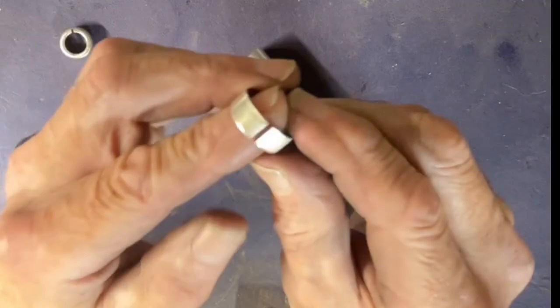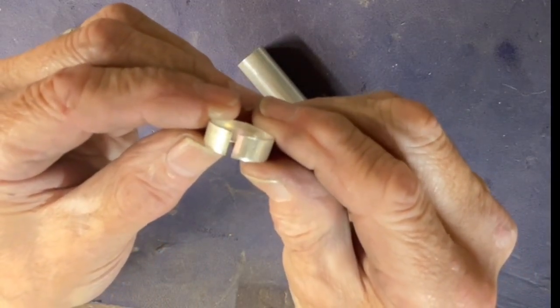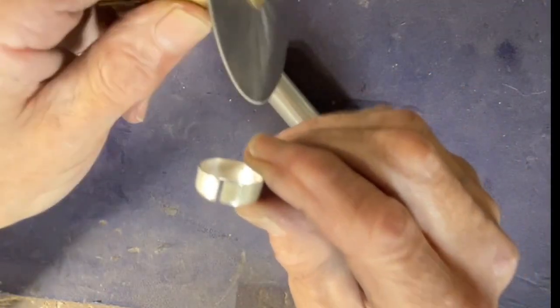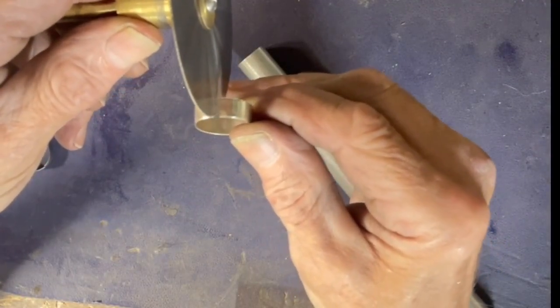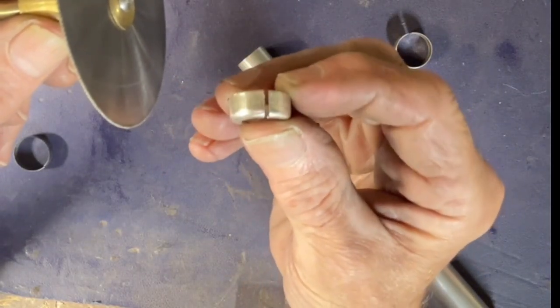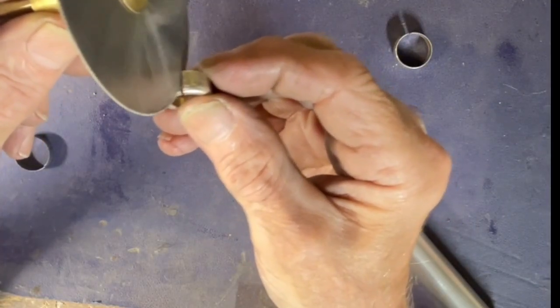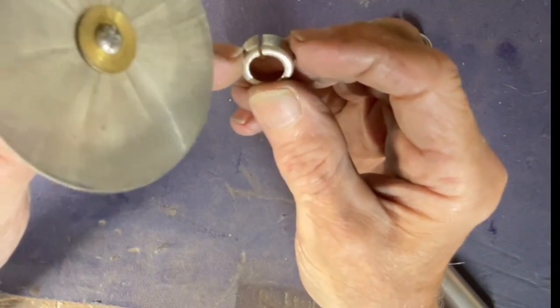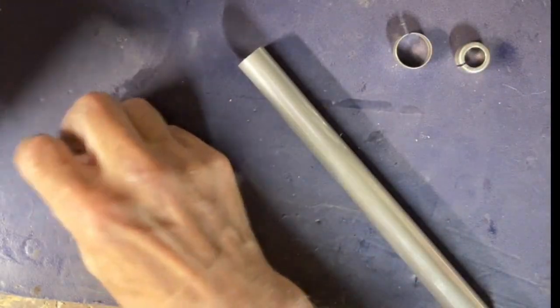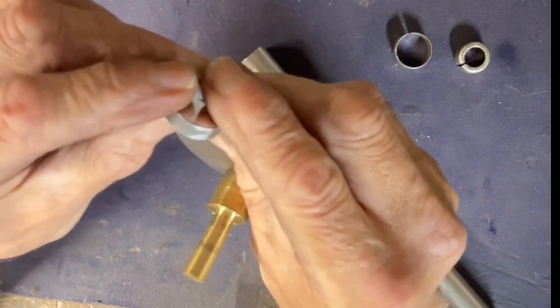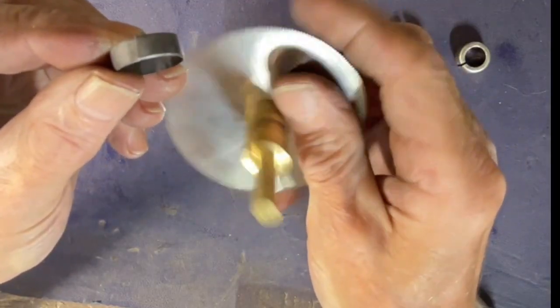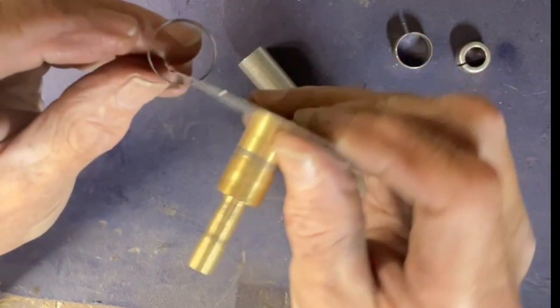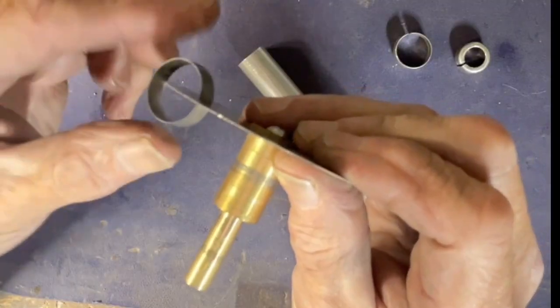And you can see that when this was cut, it will spring open, even at the bottom end. This was the saw that was used, which is 14 thousandths of an inch, and it has a fair amount of spring. Likewise, the top has sprung open, really about the same amount, so that's kind of surprising considering this is the part that was squeezed down the most. If you heat treat or stress relieve the tubing, then the gap is almost exactly equal to the width of the saw here, meaning that it neither expanded nor contracted. The same thing with the top.